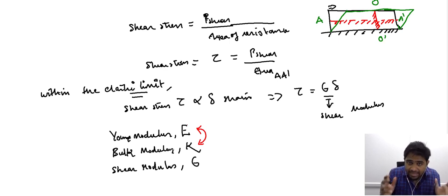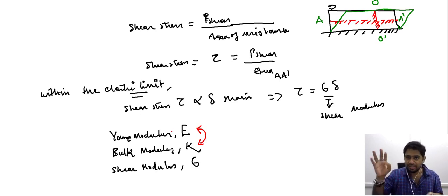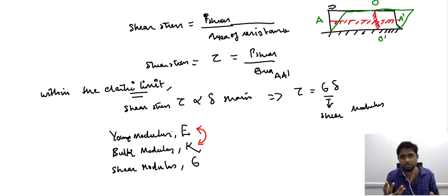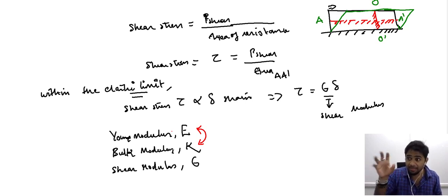So in that case, when you have an accurate estimation of the Young's modulus, the relation that we have derived helps us estimate the corresponding bulk modulus from the Young's modulus alone. So you have a machine, it can calculate only Young's modulus, but what you desire is bulk modulus. Since you already know the relation, it is possible for us to calculate the bulk modulus from the Young's modulus. So the experimental setting or the study that we are doing should not restrict us in achieving our desired goal, and this relation helps us achieve our desired goal, that is to know the bulk modulus from the observed Young's modulus.